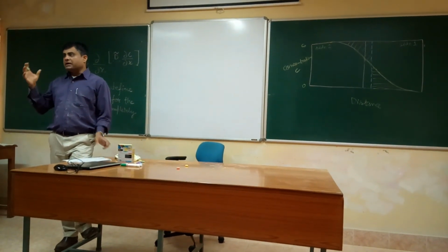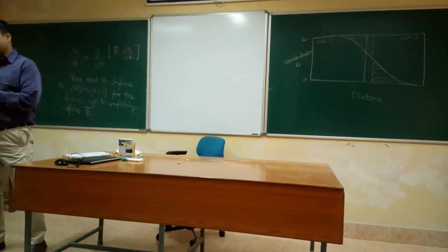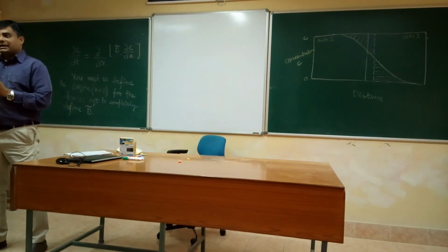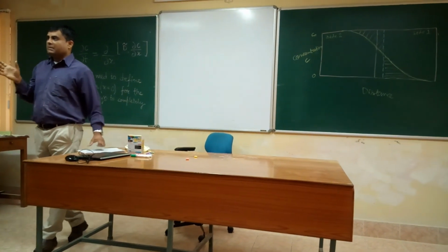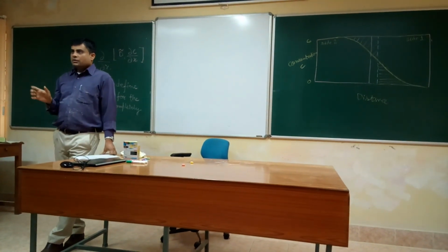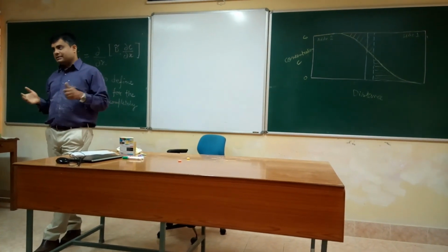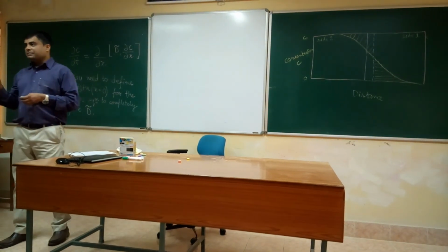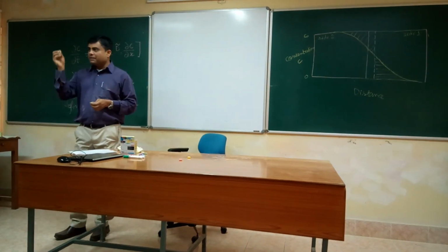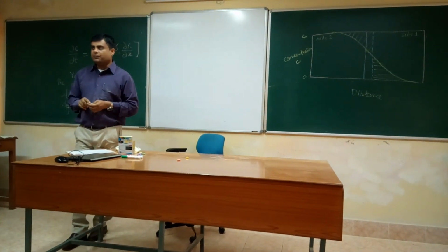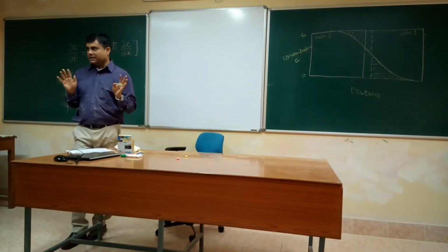What we do is, on a particular plane surface, we put a thin layer of radioactive isotope, and usually the bulk material is a single crystal of that metal or a homogeneous alloy. To avoid the grain boundaries, we either use a single crystal or very large grains, so that the grain boundary contribution per unit volume is negligible. You anneal after putting a thin layer of radioactive isotope, which is called the tracer, for a specified time at a particular temperature.